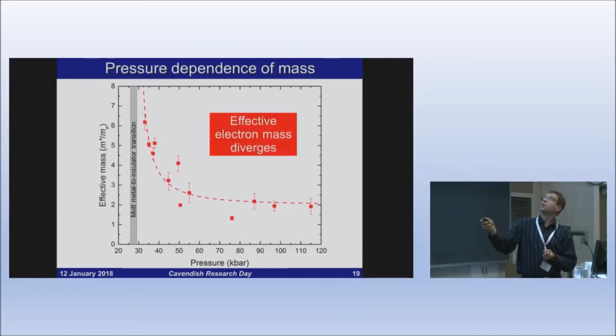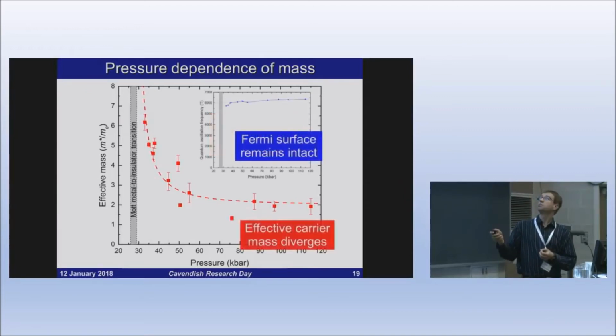On the other hand, we can measure the effective mass by measuring the amplitude of this oscillation as a function of temperature. We can infer an effective mass of the carriers, which we see here appears to diverge as we approach the metal-to-insulator transition. So it seems that these carriers are getting heavier and heavier and thus effectively slower and slower until they finally stop, which is what drives the metal-to-insulator transition. And this is basically the main result of the work, that the Fermi surface remains intact. We still have carriers, but they're frozen in place. They become heavier and heavier until they stop.